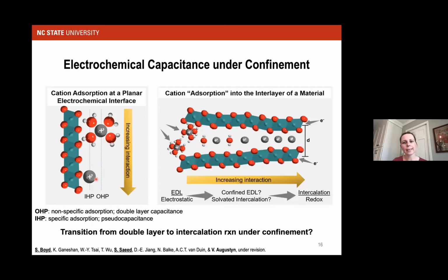On the other hand, what we're looking at here is, of course, a situation where you don't have a planar interface. And while what's happening at the outer surface might be explained by the kind of picture I'm showing here, what's going on under confinement in layered materials, particularly ones that contain water as birnessite does, we think is quite different. It's actually more of a transition and shows the relationship between the electric double layer adsorption processes at the outer surfaces versus a continuous desolvation of the cation. So at the end, you're left with something that looks like an intercalation reaction, basically determined by the solvation state of your cation and the interaction distance between your cation and your electrode. So that's a question that we have: is this a more appropriate discussion of electrochemical capacitance when you know that you have a confined electrolyte situation taking place?